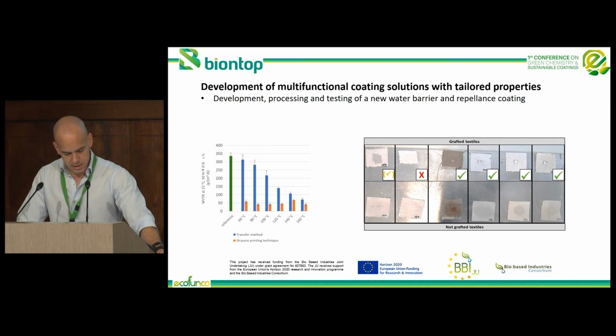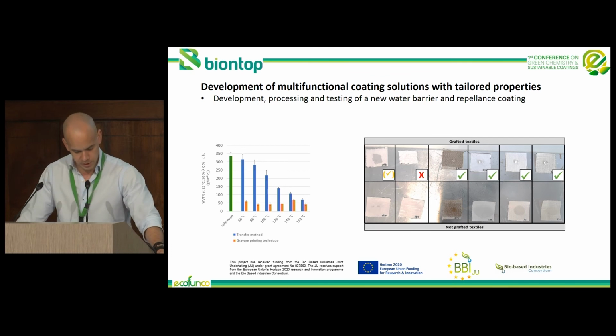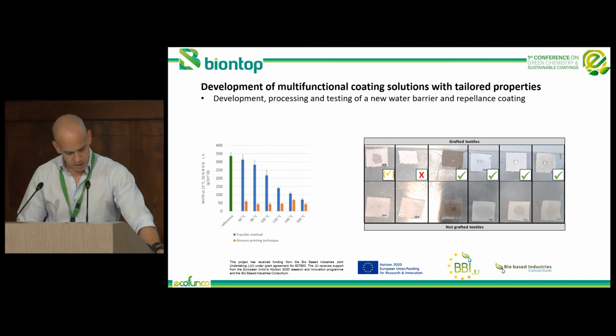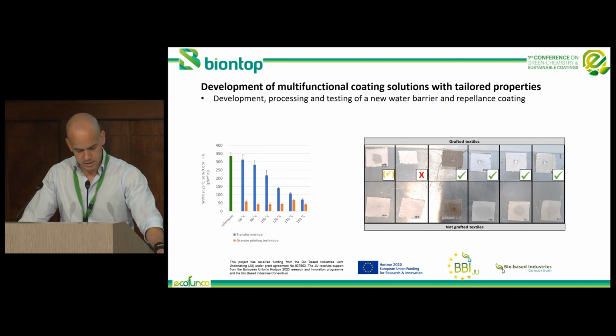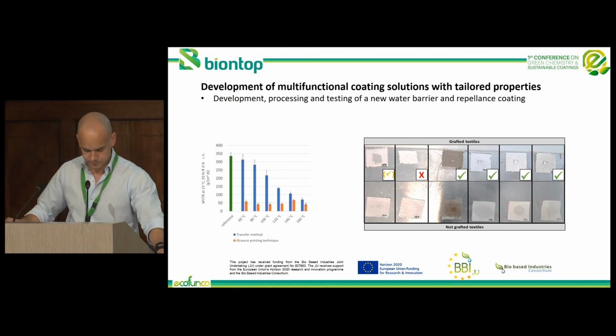A fatty acid-based humidity barrier nanoscale coating for films, resulting from solvent-free chemical grafting, is also being developed to enable deposition of monomolecular layers that drastically improve the barrier properties. We are applying the grafting on wheat protein-based barrier coatings, as well as on PLA films and textiles to reach the optimum value of oxygen barriers. The fatty acid grafting, as well as polysaccharides, will also be tested on PLA textiles as aroma barrier.